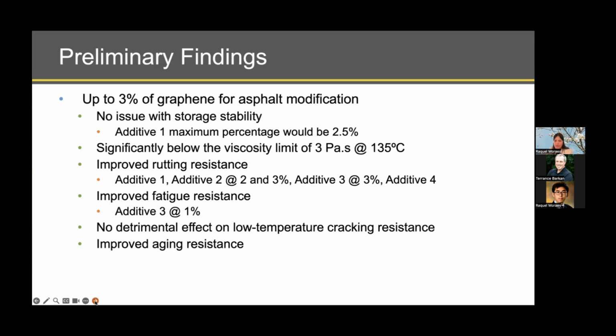The only one that showed a difference of more than 10 Celsius degrees between top and bottom portions after the storage stability test was additive 1, where we saw that for that specific additive, the maximum percentage that could be used for this specific binder would be 2.5%. We saw that for all the additives at dosage up to 3%, we saw no negative effect on the viscosity, where all the blends show viscosity results at 135 Celsius degrees way below the limit of 3 Pascal-seconds.